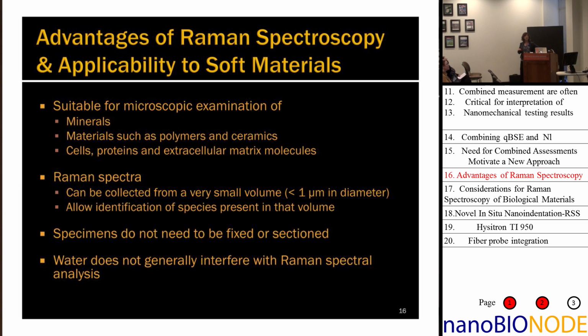What that does is you get this scattered light that is deviated off of the surface, and you can measure that with some really high performance detectors and analyze it with the fancy software that you get from your Raman company. But the point is that you get a spectrum over certain wavelengths that you prescribe. In my lab, we're using a near UV laser, and there's another, longer wavelength, near IR, I apologize, laser to collect spectra and then interpret those. I'll tell you how we're doing this in conjunction with our materials.